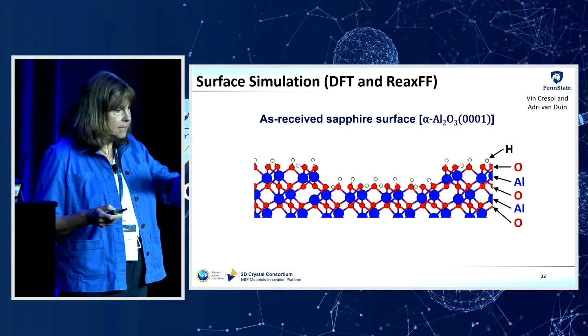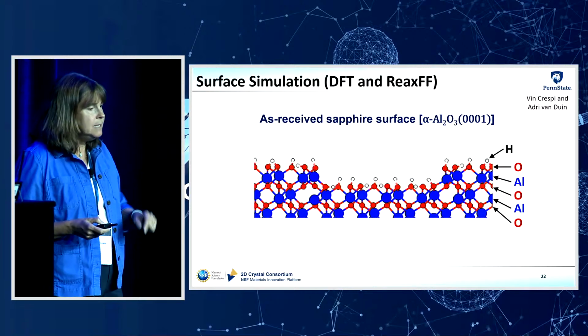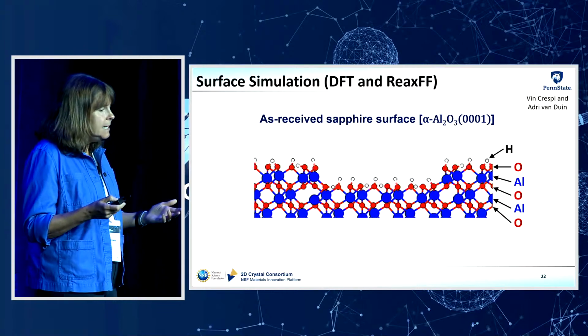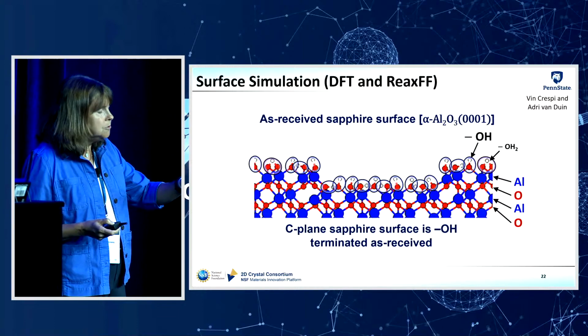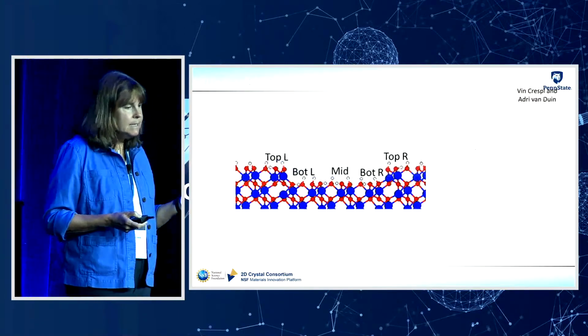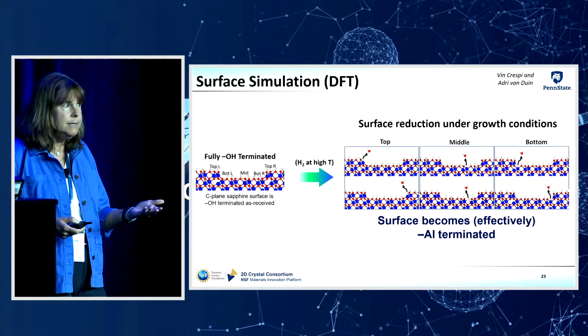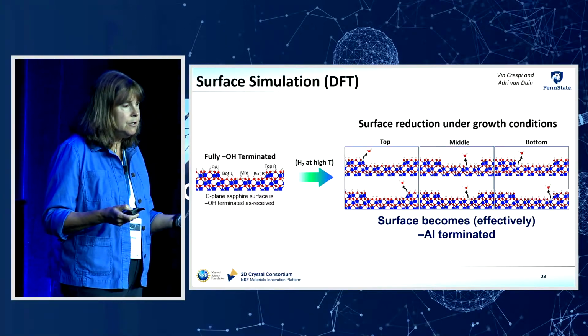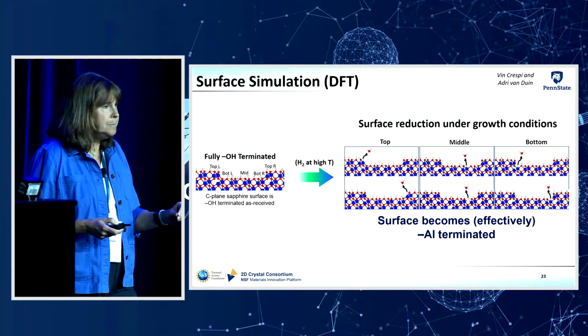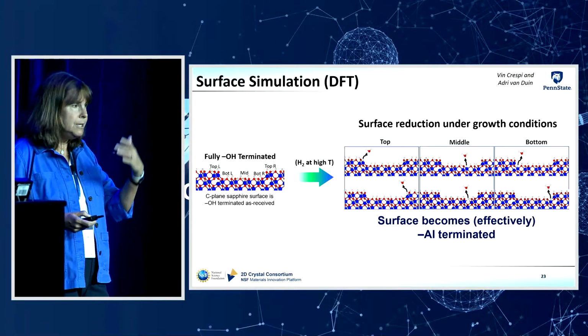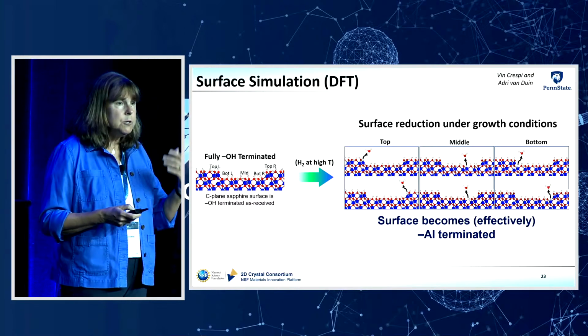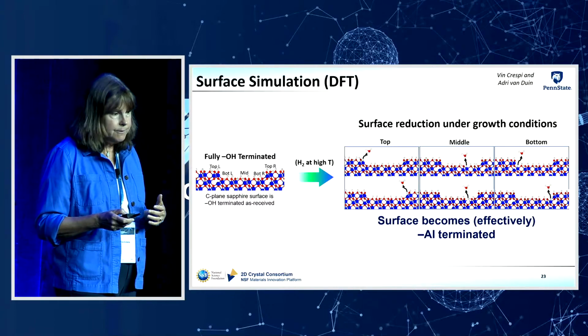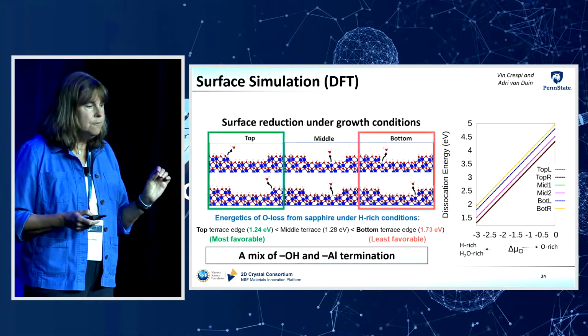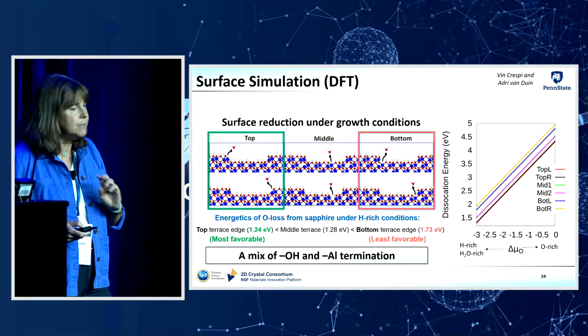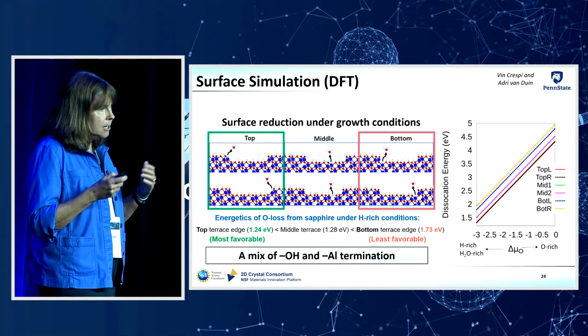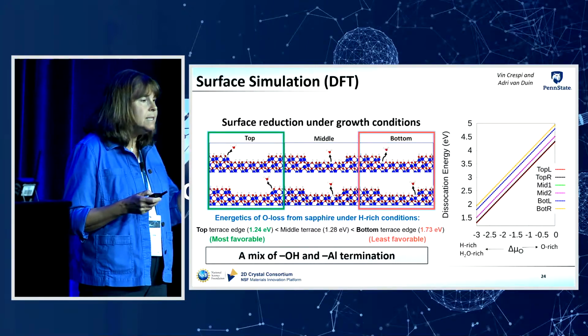So in this model, this is a cross-section of the sapphire surface where we have steps, right? We have these atomic steps. And the sapphire that we receive is terminated with hydroxyl groups. But when we take this sapphire that's terminated with hydroxyl groups and we put it in our MOCVD reactor and we heat it up under hydrogen to 800 degrees C, the hydrogen reacts with the hydroxyl groups and it removes them from the surface in the form of water. So we're reducing the surface and the surface becomes aluminum terminated. So we're changing from a hydroxyl terminated surface to an aluminum terminated surface. And they took a look at this process of hydroxyl removal as a function of location on our step sapphire surface. And what they found is that the location where hydroxyl group removal is most favorable is the top edge of the step.